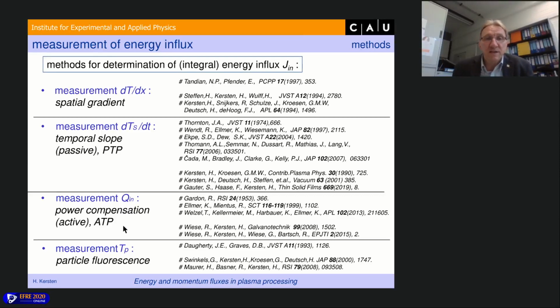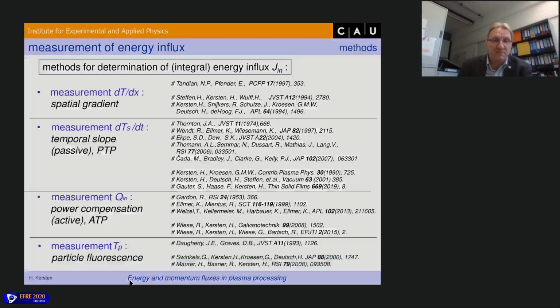But you can also do that actively, which we call an active thermal probe. For instance, you heat your probe to a certain temperature, and if you get an additional energy flux from the plasma, then you need less power to heat your probe because there is an additional power flux from the plasma. And so you can measure the jump in the power as a number for the incoming power from the plasma. I will show you an example. And you can use tiny particles, microparticles, for instance, where you can measure the equilibrium temperature, as I already explained.